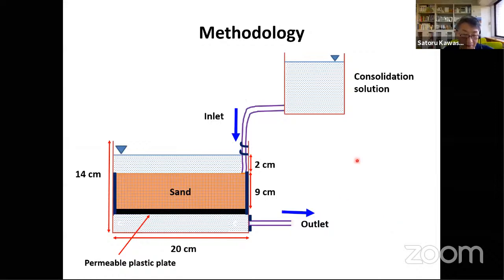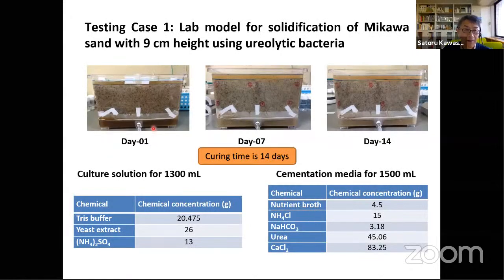This one is a schematic model test diagram. This area indicates the sand ground model. We prepared a clear, transparent box and filled it with natural sand. The height is 9 centimeters. At the lowest base we seated filter paper. Then we added consolidation solution and bacteria solution from the top and the outlets. These were the results, day 1, day 7, day 14. In total we continuously conducted 2 weeks.